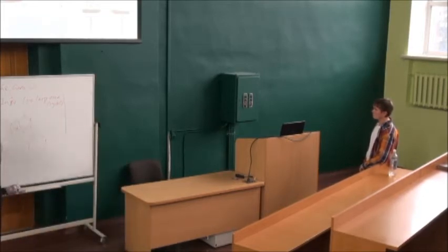You have one anvil like this, then you just put them together and put your material here. Then just tighten it. By doing that, you can create pressure of almost 100 gigapascal. This means 10 to the power 9. That's right, 100. So that's a very huge pressure. Under this pressure, you can make new phases of material.